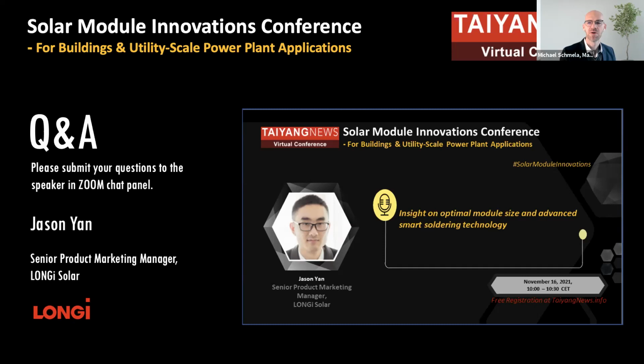Okay. What else do we have? There was one question regarding encapsulation, EVA versus POE. Are you continuing to use EVA as encapsulation material, or are there plans to use others? Basically, for our bifacial module, we still use POE encapsulation, which is more reliable and better in PID resistance. Normally for the monofacial module, we still use EVA.